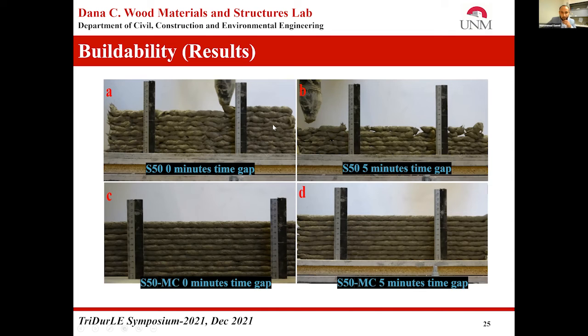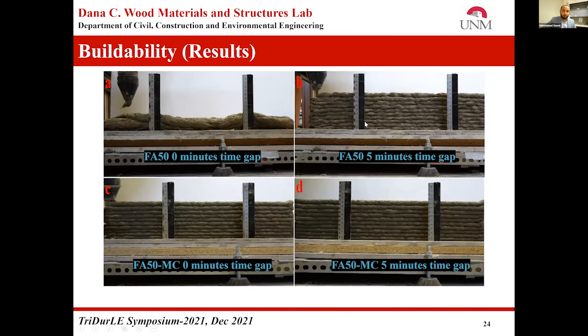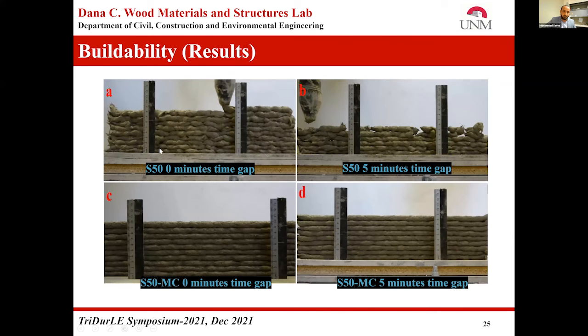At this point, we can conclude another thing, that the mix design also has a significant effect on the printing quality. If we compare the standard ECC mix that has fly ash with the mix that has slag, you can see the difference in printing quality, that mix ingredients also affect the printing quality of the filament.